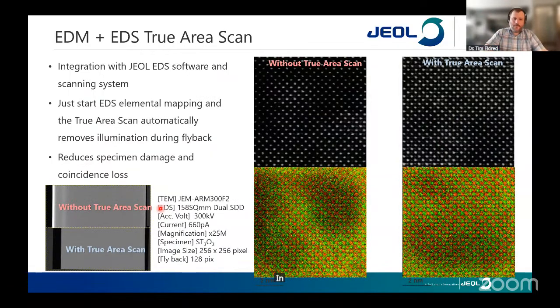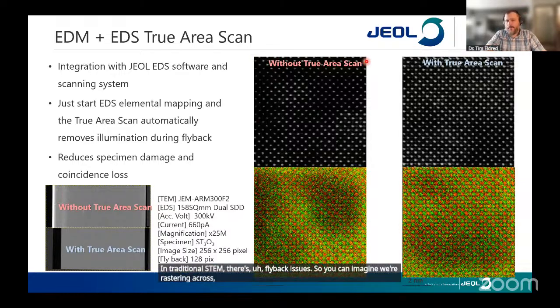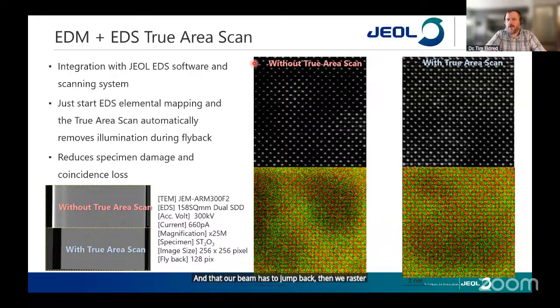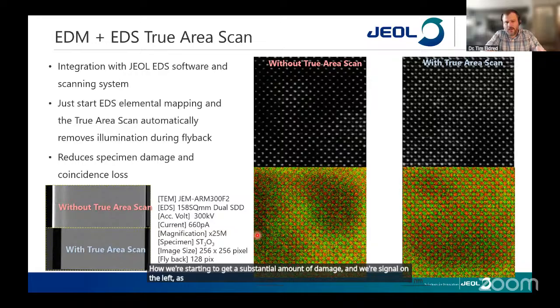In traditional STEM, there's flyback issues. So you can imagine we're rastering across, and then our beam has to jump back. Then we raster across, and then our beam jumps back. What this ends up with is a non-uniform application of dose, shown down here, where we're overdosing this left area because it has to move back. It parks for a tiny bit, and then it goes across. This leads to extra damage to the left side of a window versus the right side, which you can see in this EDS map, how we're starting to get a substantial amount of damage and worse signal on the left as compared to the right.